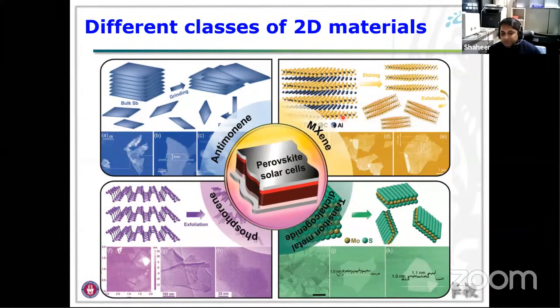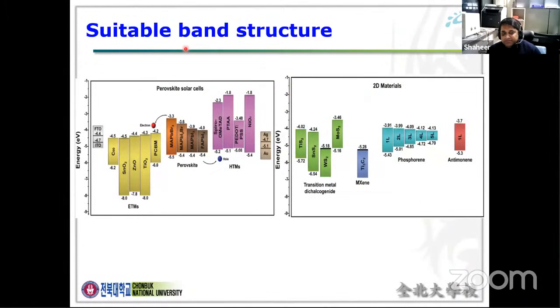I will show you some examples of why these materials are promising. If we compare the existing perovskite solar cell structure with the band gap of these 2D materials, you can see that TMD materials, MXenes, and phosphorenes have band structures almost similar to our existing perovskite solar cell components.